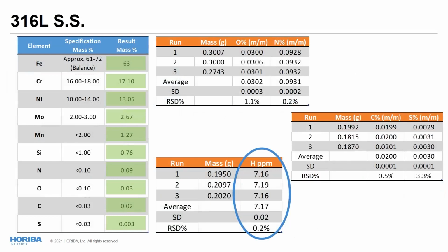Last example of powders that was used for initial control was a 316L stainless steel. And again, XRF and elemental analyzer were both showing that the powder can be introduced into the system with no harm, and hopefully a good specification for the final part. And again, we can see very, very good